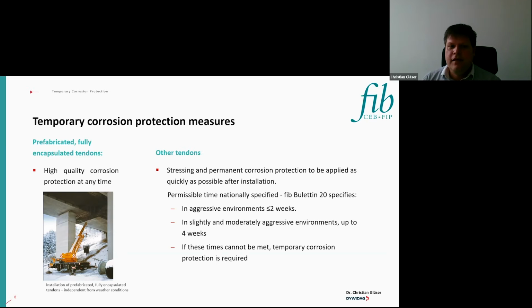For the other cases, we need to make sure that we are taking care that the time between installation, stressing, and corrosion protection is limited. The permissible time slots that are specified, for example, in FIB Bulletin 20, are roughly 4 weeks, and in case we have an aggressive environment, this should not exceed 2 weeks. So if these times cannot be met, temporary corrosion protection is required.